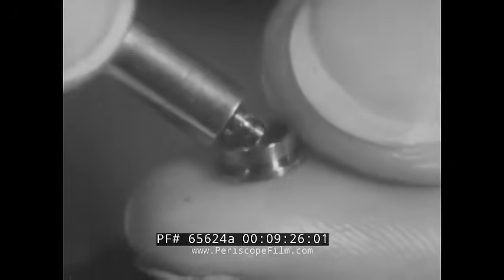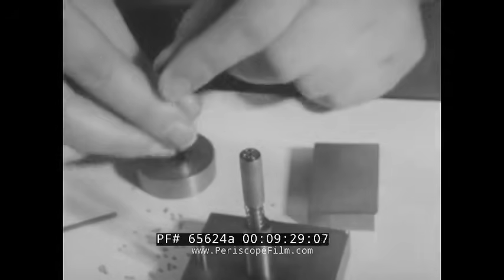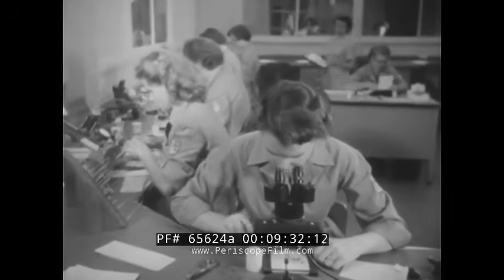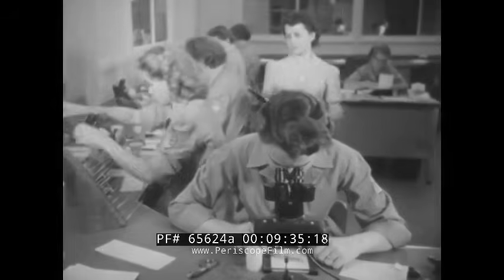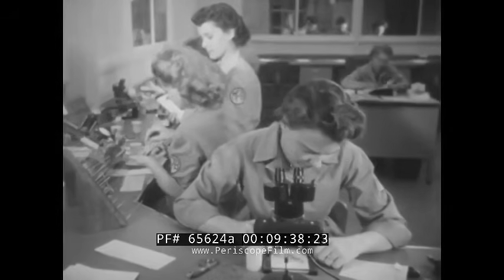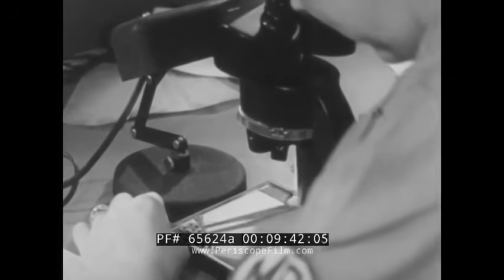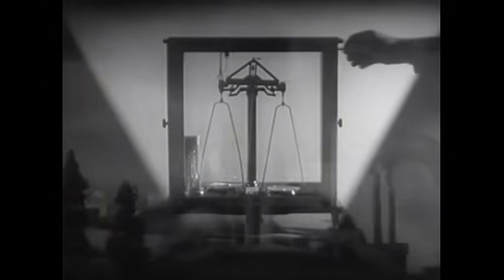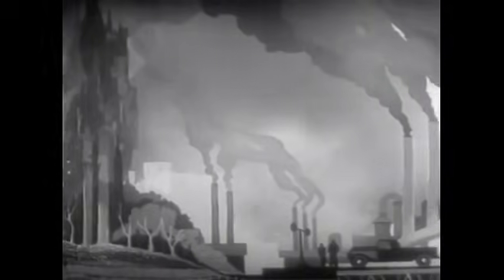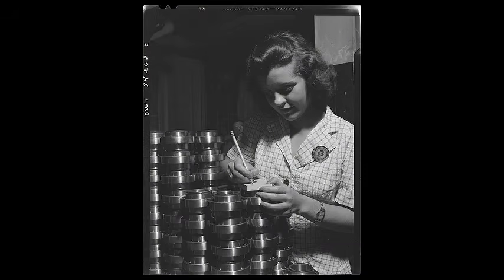The final operation is lapping, and it is the same idea again, taken to its extreme. The balls are rolled once more between plates, one fixed, one rotating slowly, but now the abrasive is exceptionally fine, a slurry of very fine grit or diamond dust, and the material removal rate is minute. Lapping is not shaping. It is the last correction, taking the balls from very good to as good as measurement can confirm. The surfaces come out with a mirror finish, and the geometry converges to diameter variations well below a micron and sphericity to match. Then the balls are washed to remove every trace of abrasive and fluid, because a single embedded grain of lapping compound left on a bearing ball is a guarantee of eventual failure.